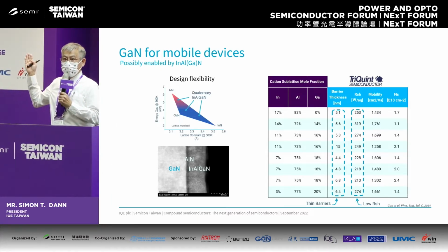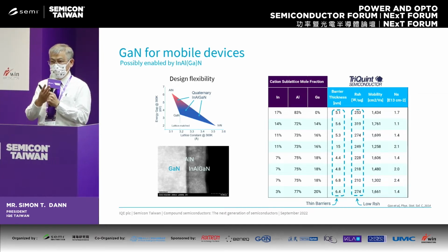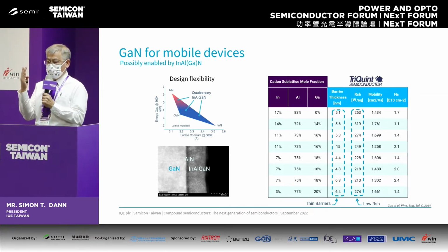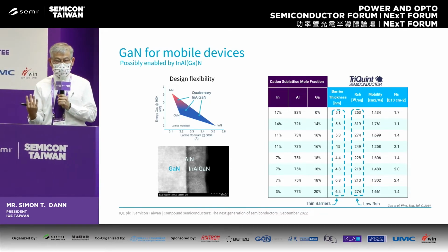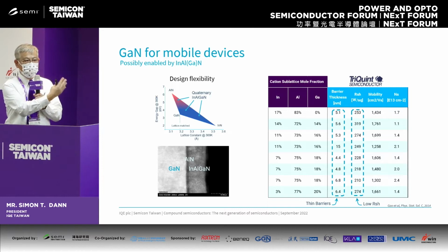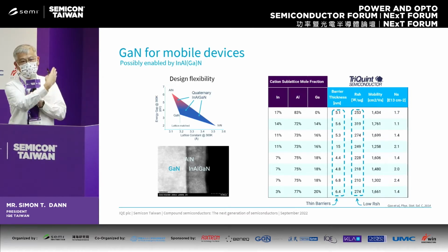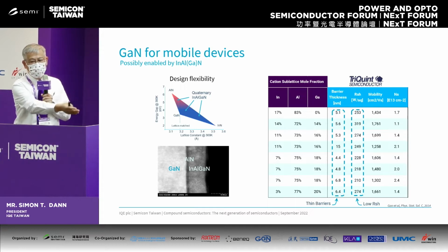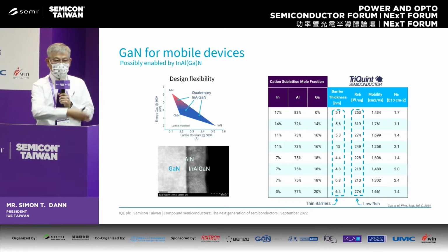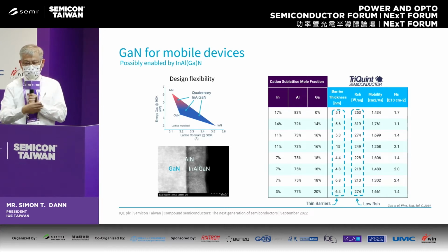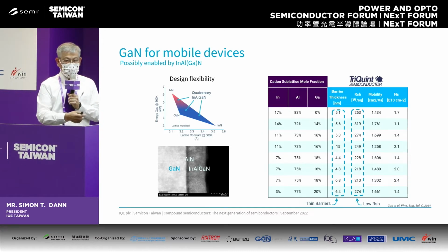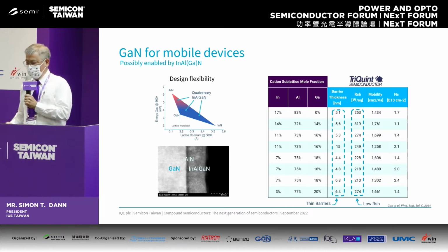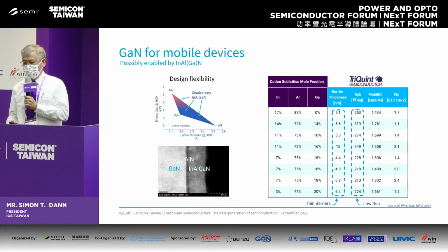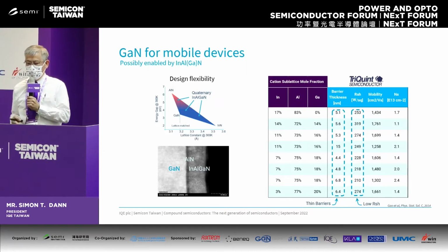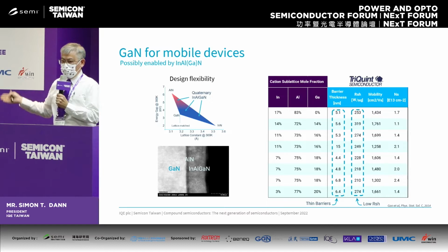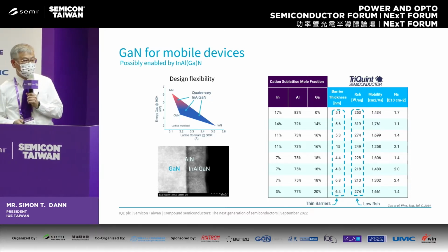This is the gallium nitride for mobile device that show you the manipulating of the indium and the gallium and the aluminum composition. So we can manipulating the light emitting the band gap from the long wavelengths, like red color, to the short wavelengths, all the way to the blue color. And just fine-tuning the composition and the lattice, and also the buffer. So there's a data show you that we are available. We are capable to manipulating those composition to deliver different color. And this was working with our customers also in 2014.